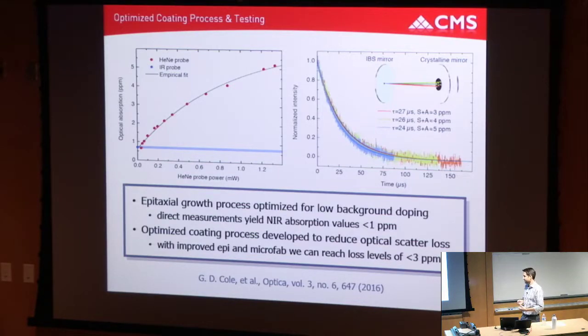The drawback of MBE is we can get ultra-low background doping, but we get small nodules, these oval defects, or these small spitted clumps of material. And so we fight with scatter in MBE-grown material. And that seems to be unavoidable at this point. So we modify the microfab process, either adding polishing steps or burying those defects at the bond interface. But with a lot of work, we've been able to push, like I said, to less than 1 part per million absorption. This is a direct PCI measurement. I'll make sense of that in a minute.